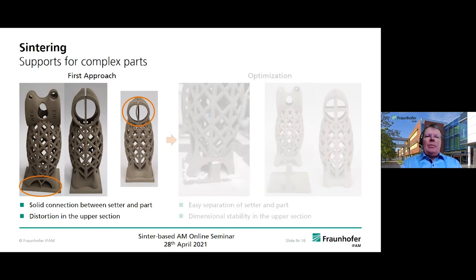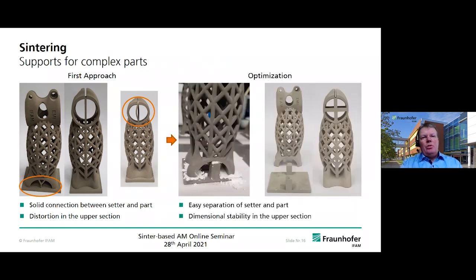This is also something we have been doing for decades: finding solutions to handle these complex parts during debinding and sintering, preventing them from warpage, calculating the shrinkage, and handling those parts and setting them inside the sintering oven in a way that we end up with high quality parts. So also there we have a lot of experience and are still learning a lot, but in this case, metal binder jetting is very close to the technologies we know, and it's the right step into this technology, combining those experiences and new insights.